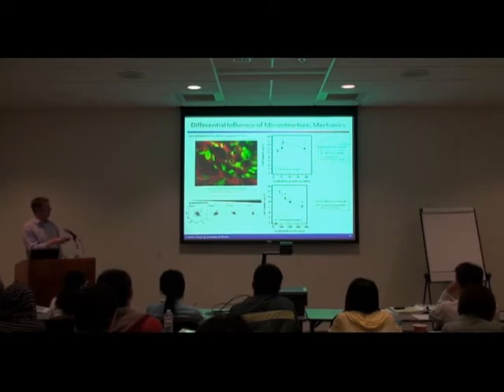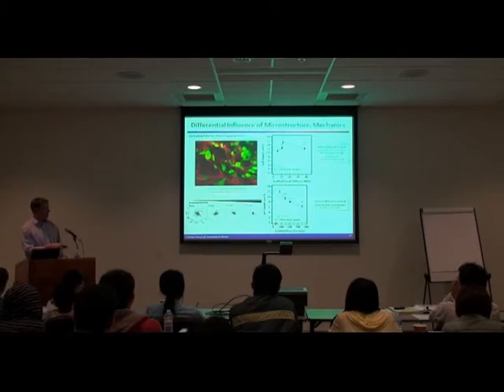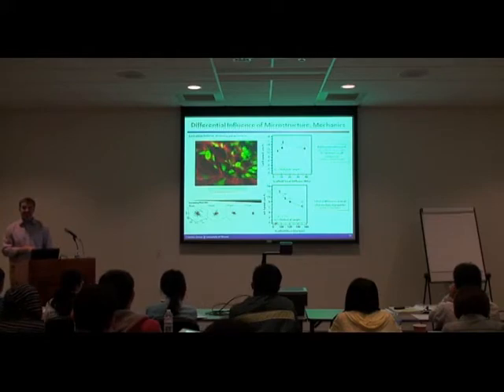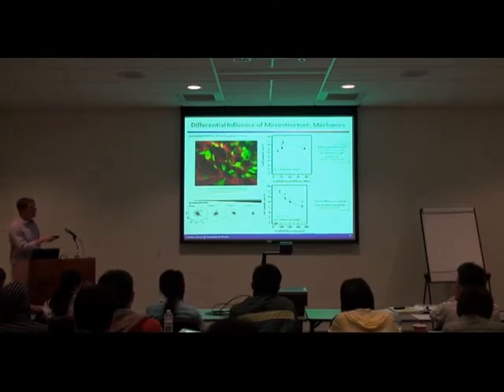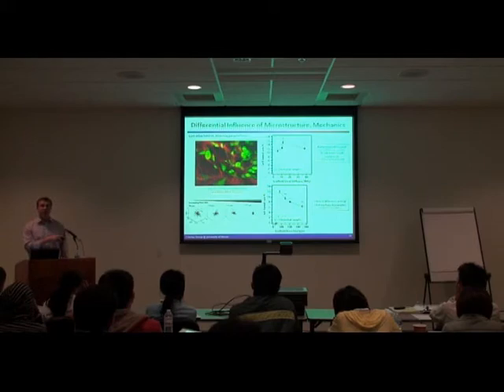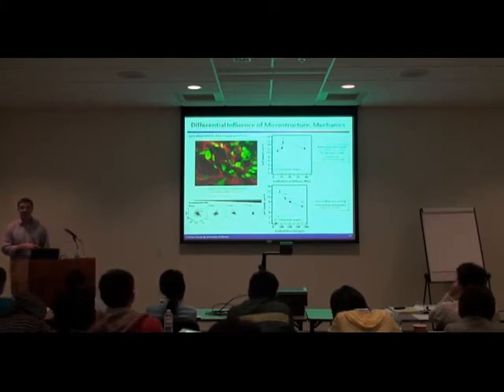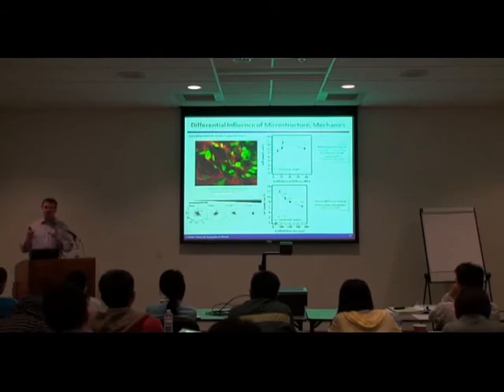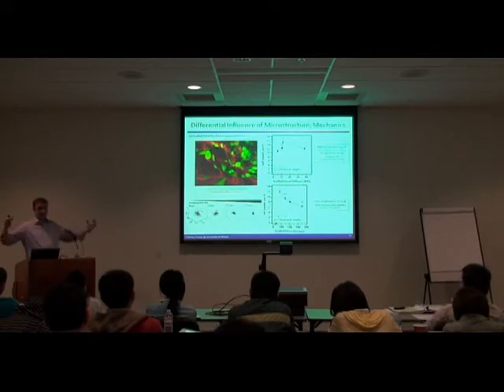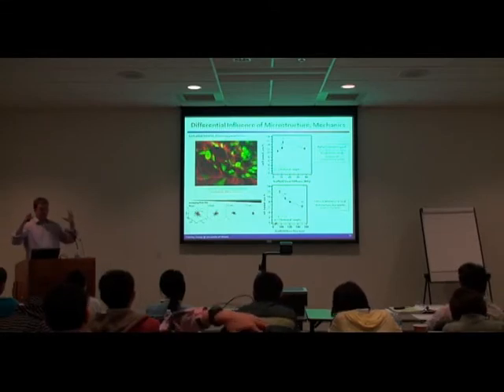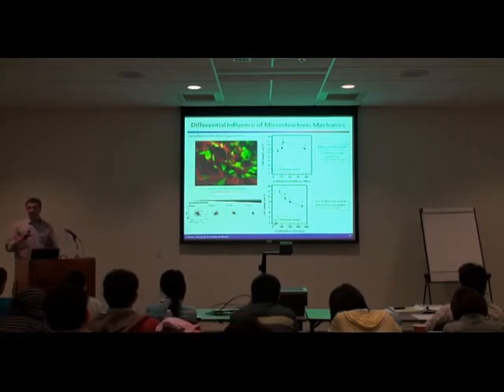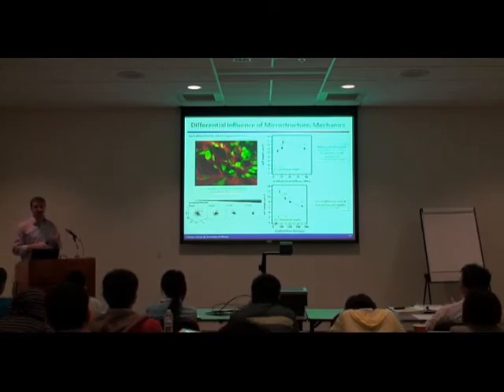We also saw that independent of scaffold stiffness, as we changed the microstructure of our scaffold from these small pores of 95 microns all the way up to 150 microns, we saw, again, significant differences in cell motility. And so this got us to start thinking that this type of relationship is actually not that surprising, understanding the mechanisms of cell migration. But this one is actually quite surprising. You have a cell that might be 20 or 30 microns in size, and it's sitting inside of a pore that's 95 microns or 150 microns. So we're talking about a cell inside a big house or a bigger house. So why is it that there are any behavioral differences that we're noticing between these scaffolds?